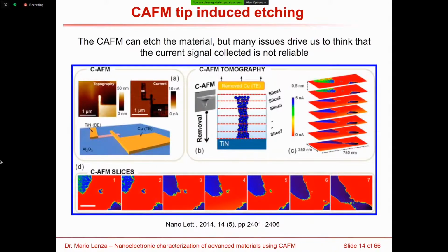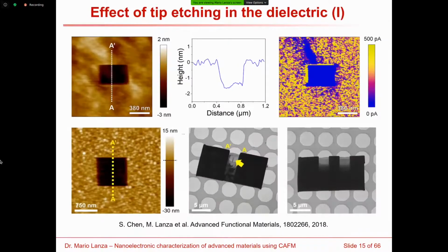Very, very useful study. However, I have to say that this etching using the tip of the AFM, depending on the materials that you use, could bring some associated problems. For example, we have observed that in some materials, the surface of the sample where you etch can change its properties. Here you can see the example of one sample in the top row. This is one sample that is just silicon. And then when we etch and we apply an electrical stress everywhere, we see that the regions where we have etched are more insulating, which means that even if it's silicon, we have changed something. We have changed the electrical conductivity at the etched region.